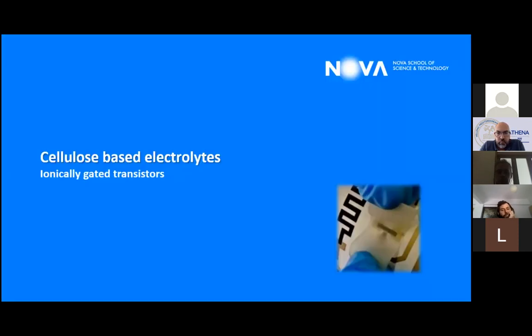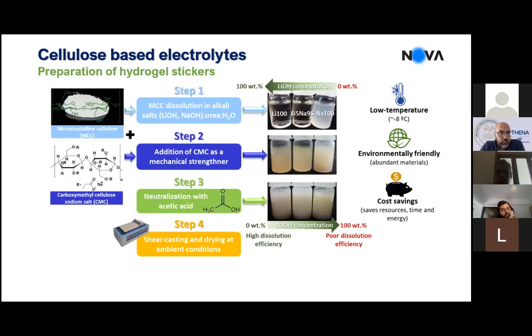Okay, so a little about the electrolytes, these electrolytic membranes that we incorporate into transistors. They are also made of cellulose. So it's a mixture of microcrystalline cellulose and carboxymethyl cellulose again, that we need to dissolve. Remember that CMC is soluble in water, but the microcrystalline cellulose, it's like pure cellulose obtained from cotton, is not soluble in water. So you need to use some nasty solvents, or use a strategy that we developed also, that is to use alkali dissolution. So it's basically using lithium hydroxide or sodium hydroxide to dissolve the cellulose.